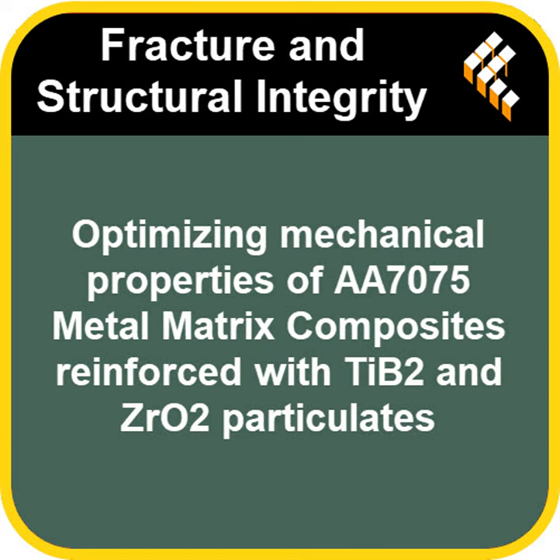Okay, so clumping is bad. What about the 2%? Not enough reinforcement. Pretty much. The 2% ZrO2 sample showed less clumping, which is good, but it ultimately resulted in lower mechanical properties compared to the 4%. It suggests that 2% just wasn't quite enough reinforcement to get the maximum benefit. So 4% ZrO2 was the sweet spot. Exactly. That uniform distribution they achieved with the 5% TiB2, 4% ZrO2 mix seems to be crucial for efficient load transfer and getting those property improvements. It's not just what you add, but how it arranges itself. Right, the microstructure really dictates the performance.